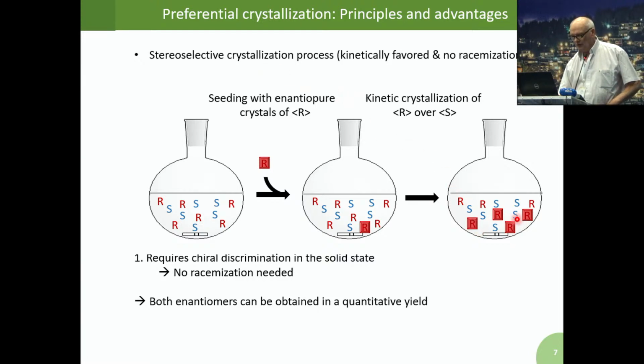And then you can collect the crystal before the other enantiomers start to crystallize. And by recycling the mother liquor that you have here with an excess of S, you can then after crystallize S, and then R again, and S, and then etc. And this process could be used at industrial scale, and it works perfectly well.